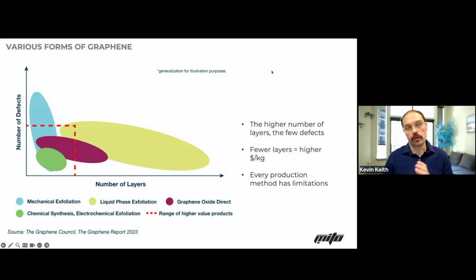So because of the different forms of graphene, you have a number of defects that are introduced, and you have a number of layers, depending on what method is used to make the graphene. It can control a lot of different methods. So like I said, with liquid exfoliation, you can have a really low number of defects, but you have a really high number of layers. Mechanical, you still have a higher number of layers, but because you're just chewing it up, you're going to introduce a lot of different defects to that. So typically, for the higher value products, so think carbon fiber composites, coatings, CVD, that type of thing, you want to stay within this red box.